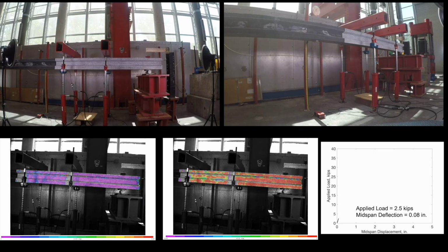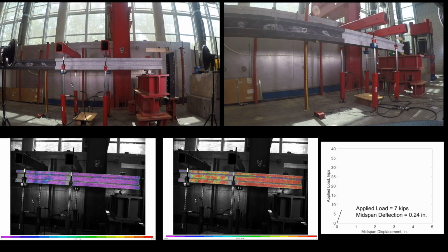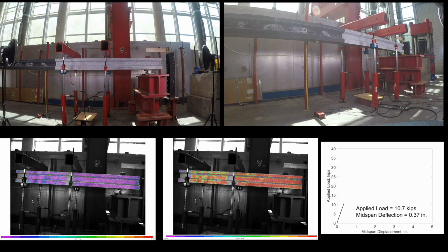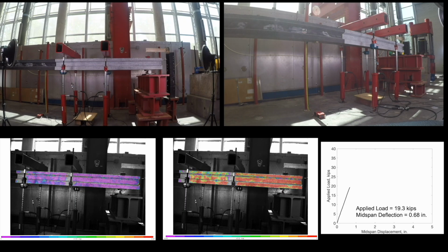Finally, here's our test actually being run. The top two images show two different video angles of the test. The bottom left image shows the principal tensile strains with low strains in purple and high strains in red. The center bottom image shows the principal compressive strains with lower magnitude strains in red and higher magnitude strains in purple. And then finally, the bottom right image shows the load displacement response of the member as the beam is being loaded. Let's fast forward a little to the cool parts.